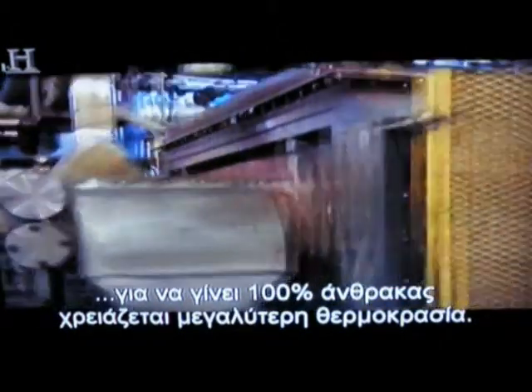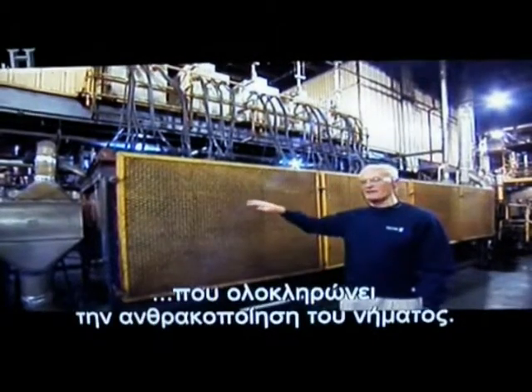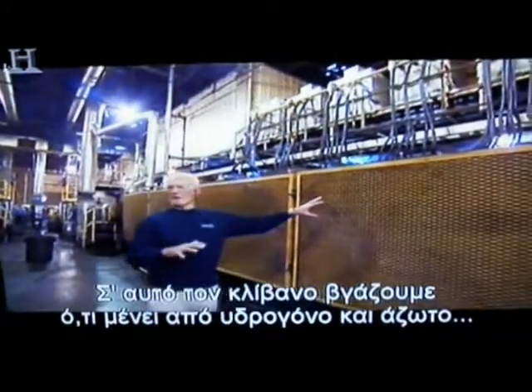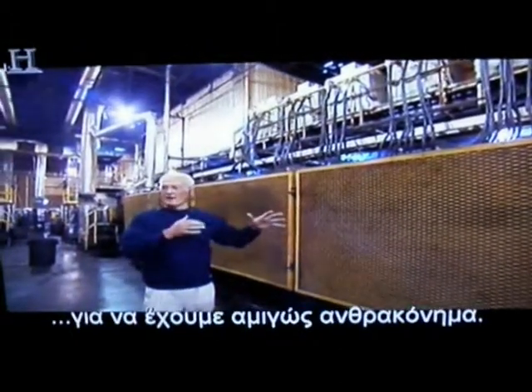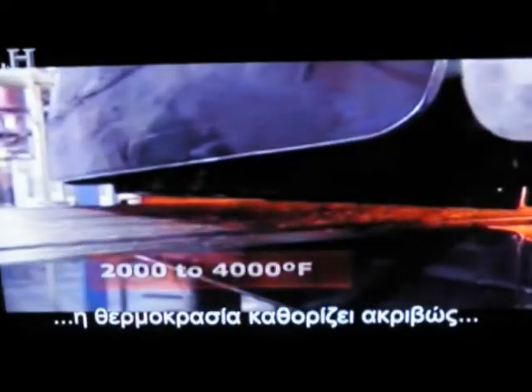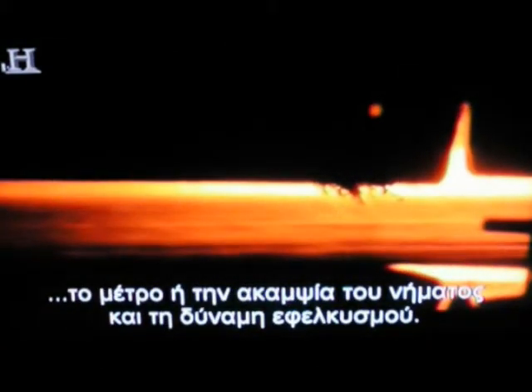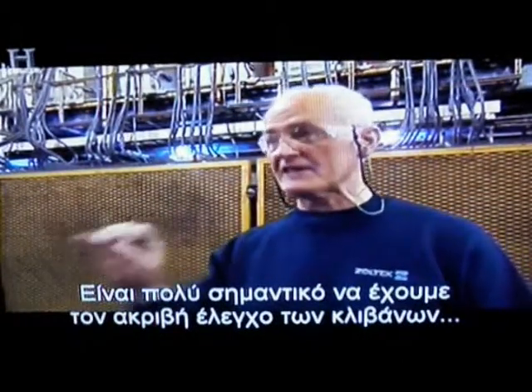Although Pyron is tough enough to stop an airplane, turning it into 100 percent carbon fiber calls for a lot more heat. This is one of our high-temperature furnaces where we complete the carbonization of the fiber — we have a total of five altogether. In this furnace we drive out the remains of the hydrogen and nitrogen to bring us up to a full carbon fiber. This is really the most critical part of the process, because the temperature we use defines exactly the modulus or stiffness of the fiber and also the tensile strength, so it's very important that we keep really accurate control of the furnaces at this stage.